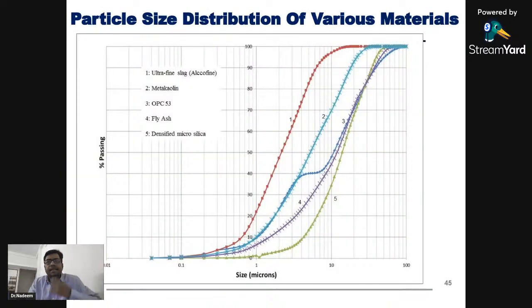These are the particle size distributions of various materials. So we have microsilica, fly ash, cement, metakaolin, and ultrafine slag, meaning Alcofine. And these are the particle size distributions, with various particles distributed in terms of sizes. It clearly shows Alcofine is quite fine compared to all other materials present.